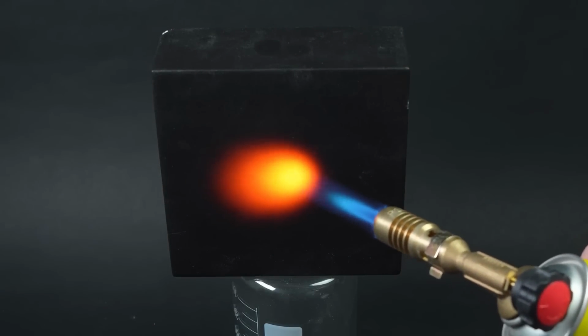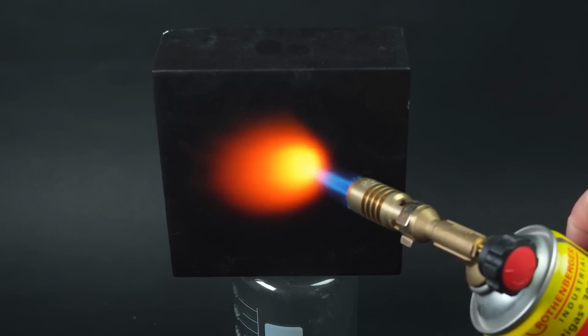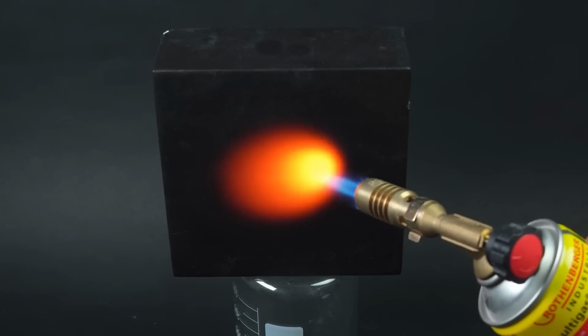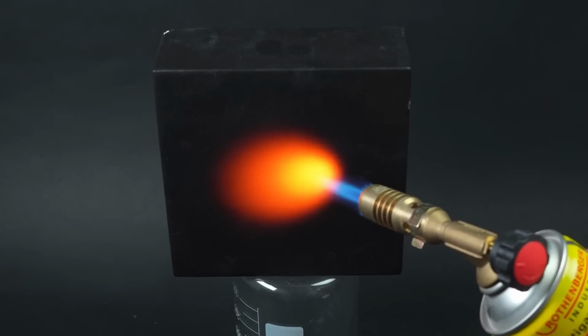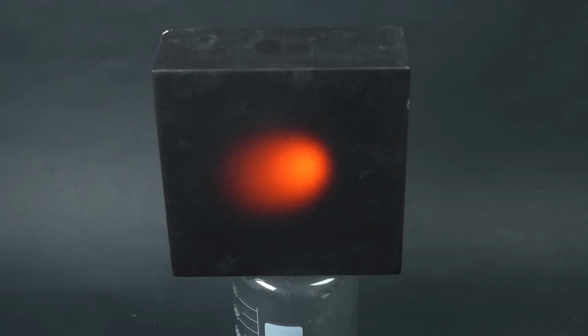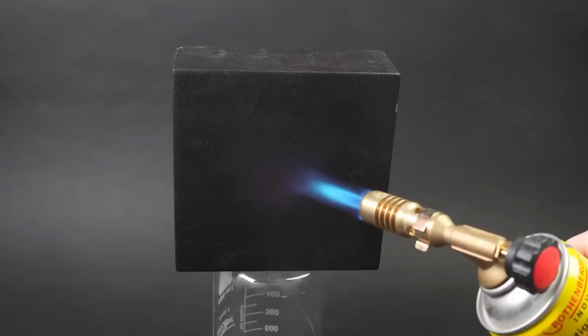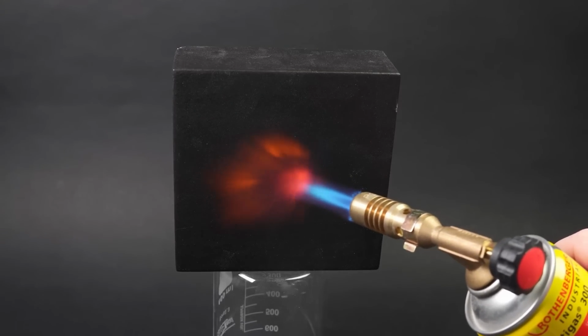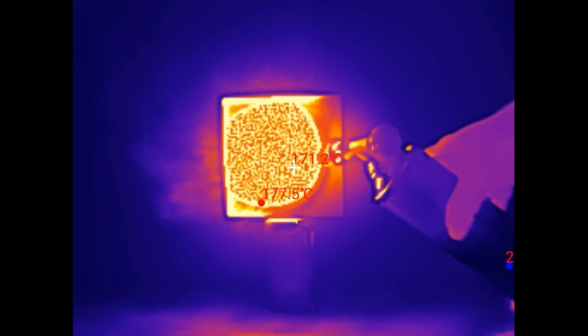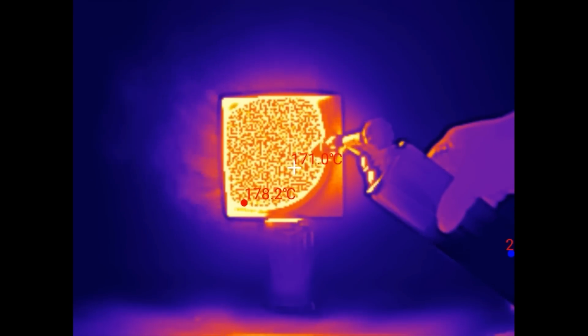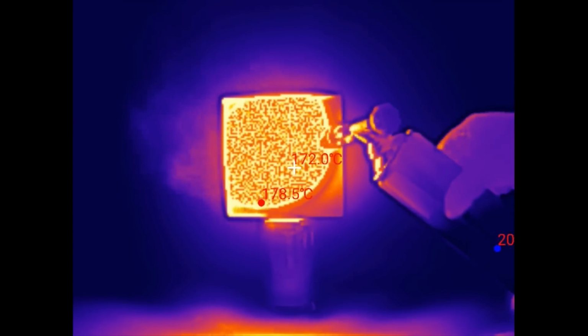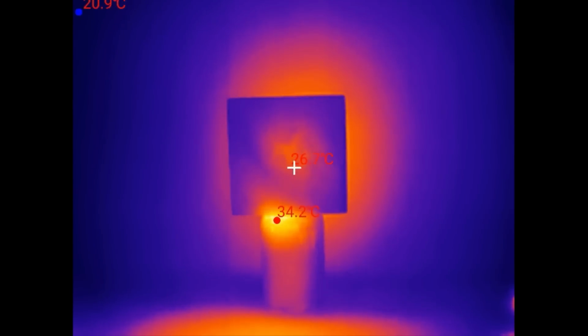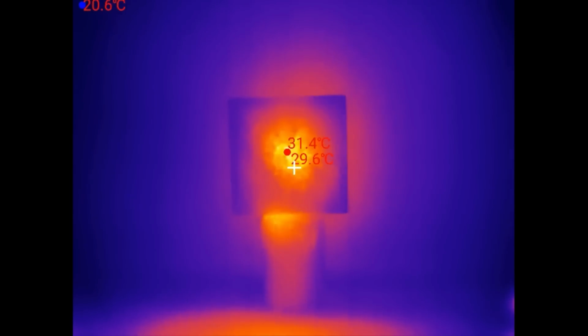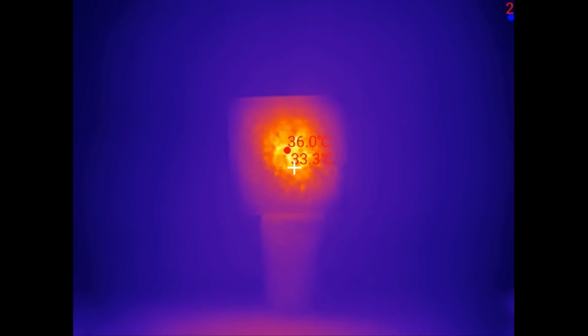Yes, apparently this is the very thermal protection, as such a tile easily withstood a minute at a temperature of 1200 degrees Celsius, and it cooled down almost instantly, which is even noticeable on the thermal camera. After cooling down, I also decided to check how this tile would heat up from a sufficiently powerful gas torch, for which I started heating it from the backside and monitoring the temperature with the thermal camera. The heating time was 2 minutes, after which the tile began to gradually heat up, but only by a few degrees. Now this is what I call thermal protection.